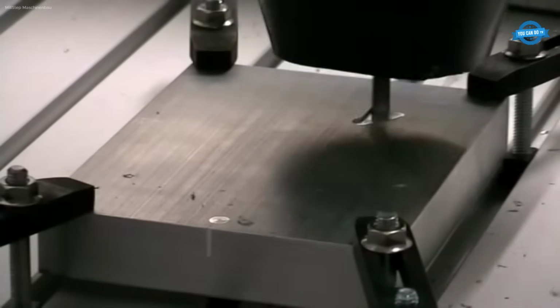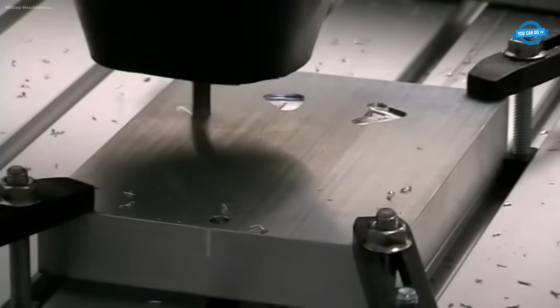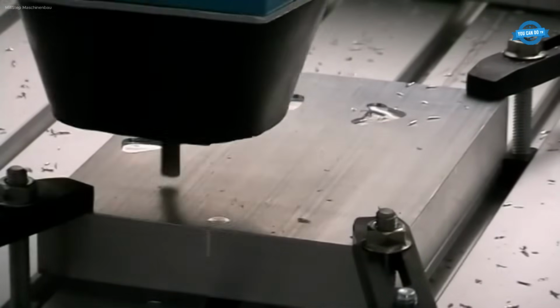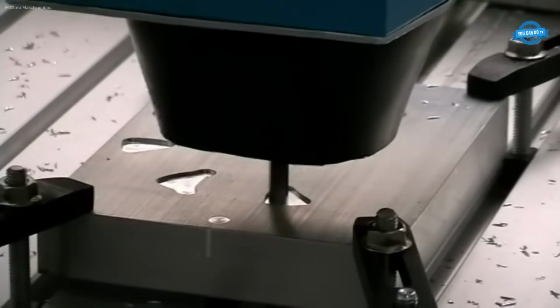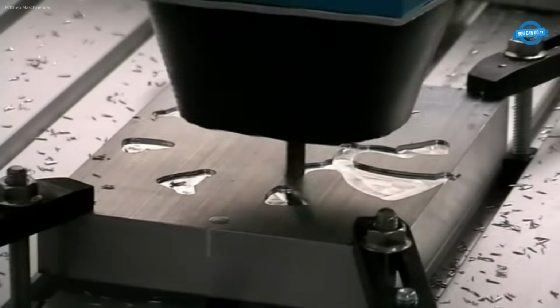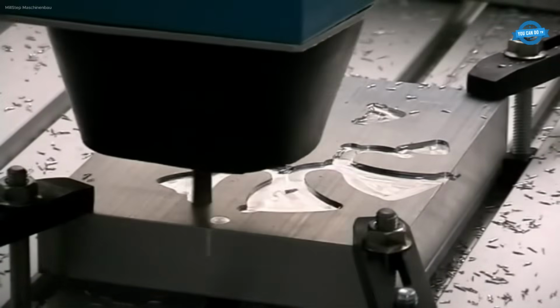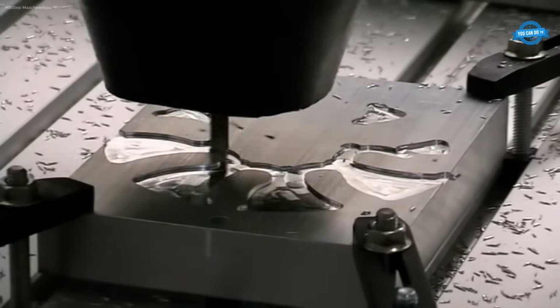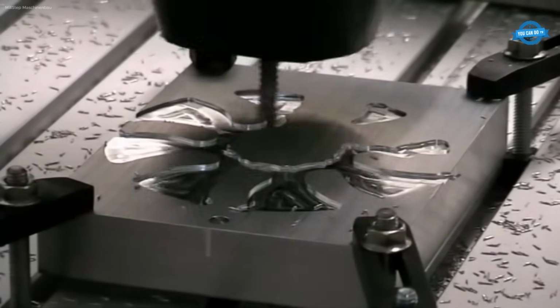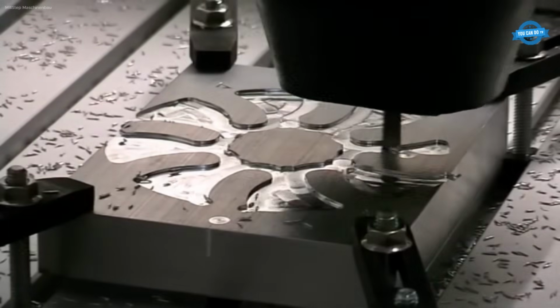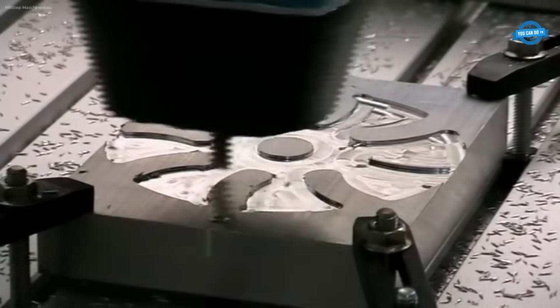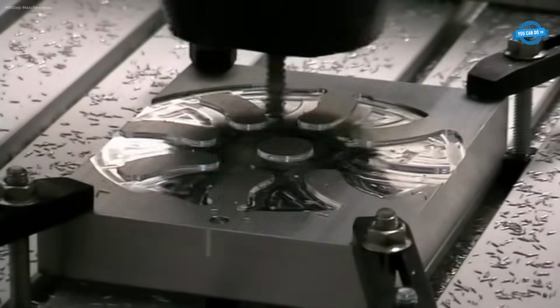Aluminum isn't just carved, it's milled with intent. On this mill-step CNC machine, a blower wheel blank undergoes a precise, multi-step process. The Z-level roughing begins first, using a 6 mm flat end mill. Each vertical pass removes 0.8 mm, with lateral engagement set to 4.8 mm. At 32 mm per second, it's not about speed, it's about control.